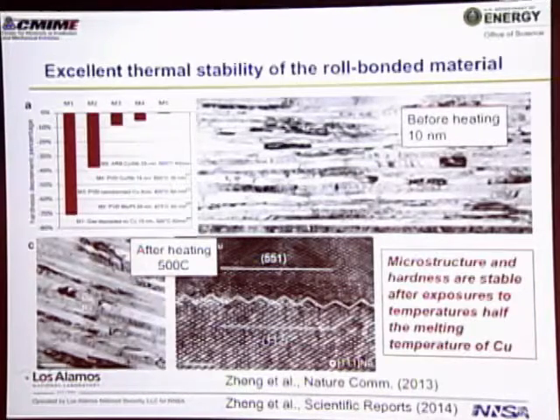What we found is that with the roll bonded material, you can have this layered structure before heating, 10 nanometer individual layer thickness, heat it to 500 degrees C, which is half the melting point of copper. That's one of the constituents. And what happens to this material? Nothing. If you're Iron Man in this case, you are in good shape.